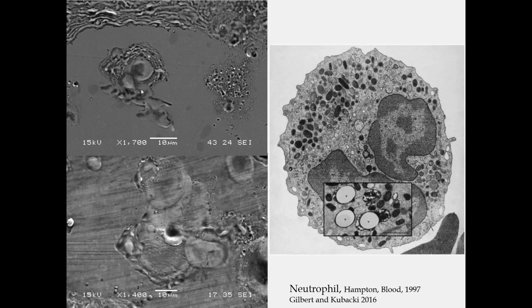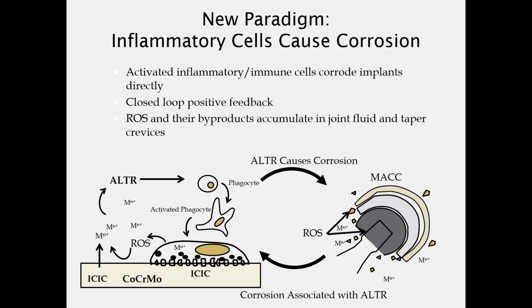And the nature of this pattern is very reflective of the organelle structure of the neutrophil in this case, where these granulocytes and other phagosomes appear to be leaving this imprinted pattern, and these larger, perhaps DNA structures are influencing this morphology here. And so we think that we have pretty strong evidence that the damage we're seeing is a direct result of cell attack on these surfaces.